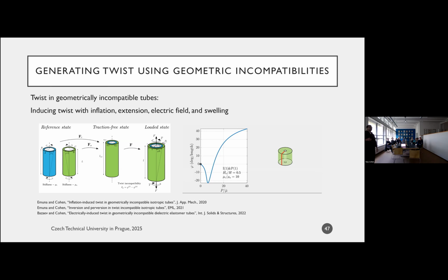And so the way we've done this is we said, let's say that I have two tubes, right? The blue tube and the green tube. These are neo-Hookean, incompressible, isotropic tubes. What I'm going to do is take the blue tube, twist it, insert it into the green tube, and then adhere them along the interface, and then let this thing relax into a traction-free state, right? So I end up with a traction-free bilayer tube. The two constituents are isotropic, but this structure is going to be loaded with a residual stress. So in a sense, you could say that I have stress-induced anisotropy.